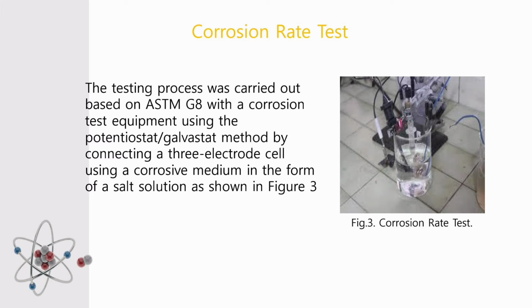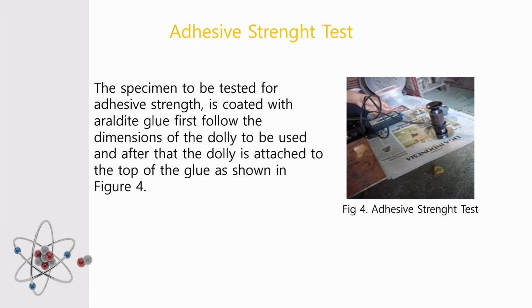Corrosion rate test. The testing process was carried out based on ASTM G8 with a corrosion test equipment using the potentiostat or galvanostat method by connecting a 3-electrode cell using a corrosive medium in the form of a salt solution, as shown in Figure 3. Adhesive strength test. The specimen to be tested for adhesive strength is coated with glue. First, follow the dimension of the dolly to be used, and after that, the dolly is attached to the top of the glue, as shown in Figure 4.